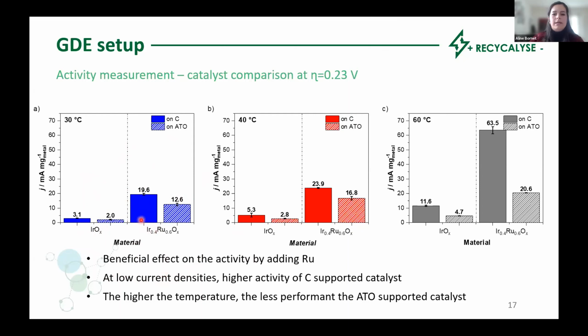Okay, so what we see here is that ruthenium-containing catalysts always exhibit a higher activity as compared to the pure iridium. Then we also see that the nanoparticles deposited on carbon always show a higher activity. And finally, we see that the ATO becomes less performant at a higher temperature. And this is the first hint that ATO support might cause problems at elevated temperatures.